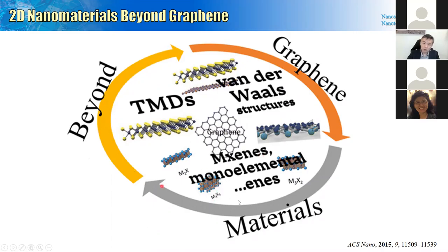But once we see these groups, we can see that in order for this 2D morphology to be stabilized, the surface has to be thermodynamically or kinetically stable. That requires this material to have a more or less inert surface. So the interface has to be Van der Waals force rather than covalent or ionic bonded. So we can call them a Van der Waals structure or Van der Waals solid. Because of this structure requirement, this left behind a big group of functional materials that has been studied over decades and shows very interesting properties, but they don't have this Van der Waals structure.